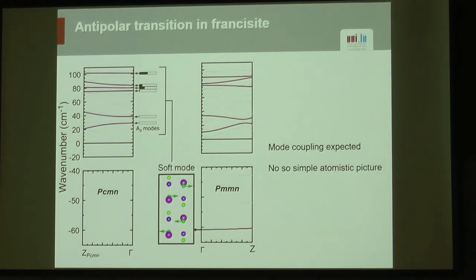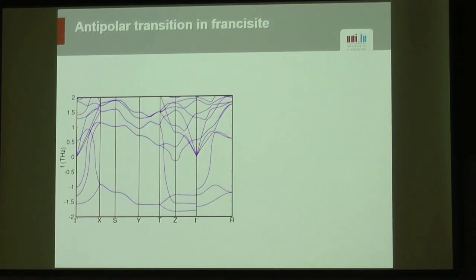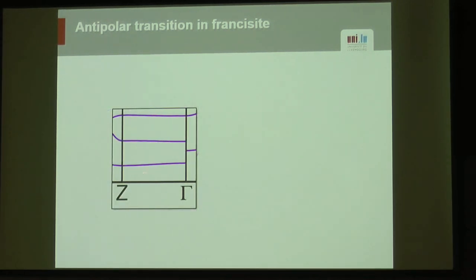Now there's a bit more to it. So here I'm showing again the phonon branches as calculated by Jorge. And I want to make a zoom on this part. So this is again between gamma and Z, and this is the soft mode. So we have, again, this one slightly lower, this one slightly higher. But then if really the phonon branch is that flat, the typical reaction is that this should be an order-disorder transition. So it doesn't seem to really match with the soft phonon that we are observing.